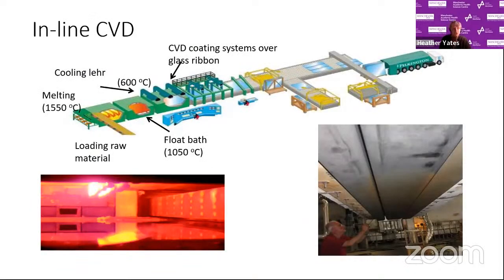Now, this picture is of continuous production in line CVD on a float glass line. So what happens is you have the raw materials, they're then floated over a bath of molten tin, but the glass gradually hardens. And then later on, you have these large coating heads. Picture on the right to show the size, where all your chemicals come through and flow over the surface of the glass, forming that thin coating.